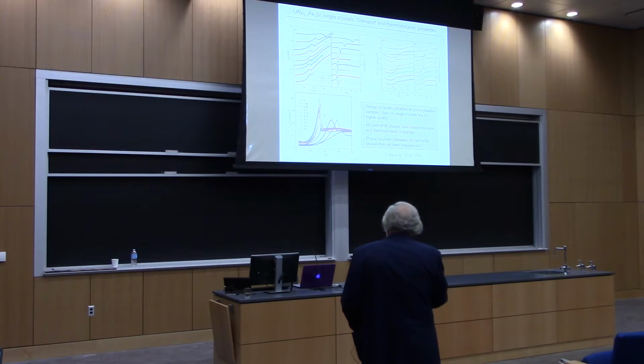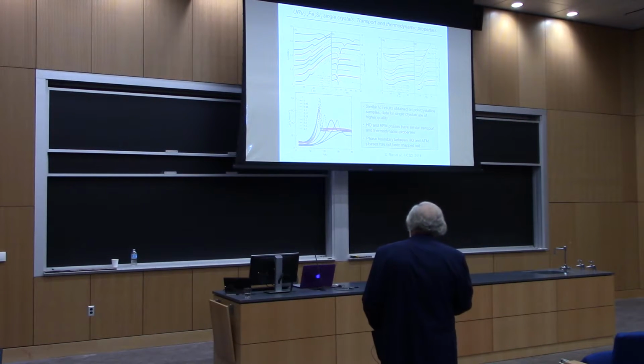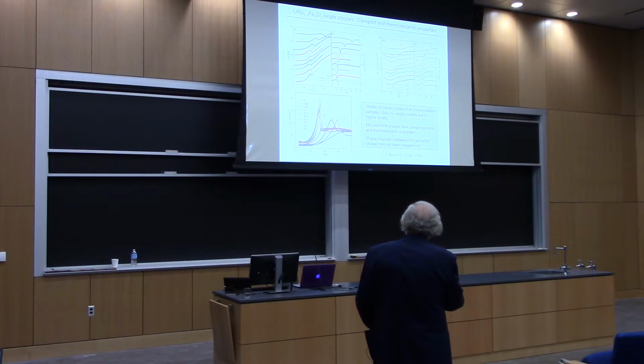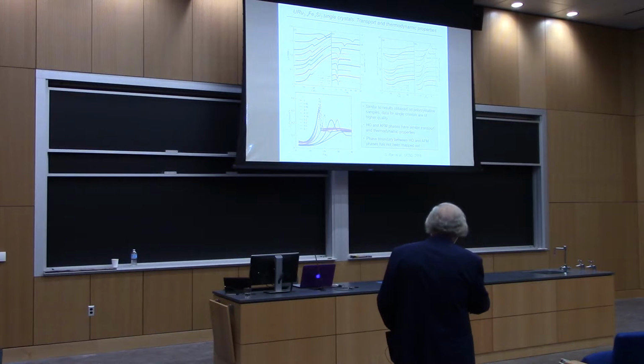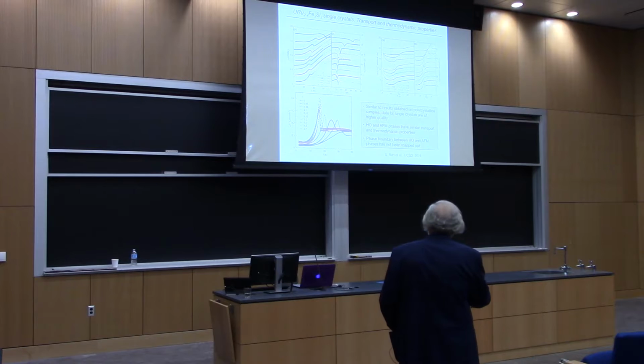And you can see that this is resistivity, so you see the features associated with hidden order and, at the higher values of x, large moment antiferromagnetism. These are the derivatives of these curves that allow you to pick out the transitions more accurately. And then this is magnetization data, and the derivative of the magnetization times temperature with respect to temperature, and that gives you features that resemble the specific heat.